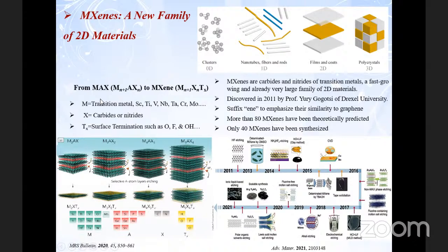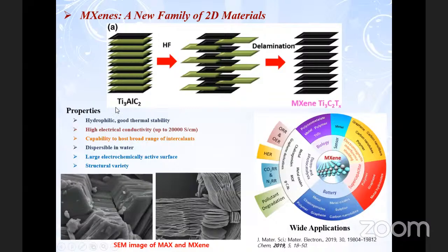When you remove the A material from the MAX phase, you will get a single layer or layer-type occurrence like MXene material, 2D materials. For example, if you have titanium carbide and you remove that aluminum by HF, you get a MXene-like structure. But the main focus is not just the application of this material, but also to develop a non-HF based method, so that we can remove HF from the synthesis route.